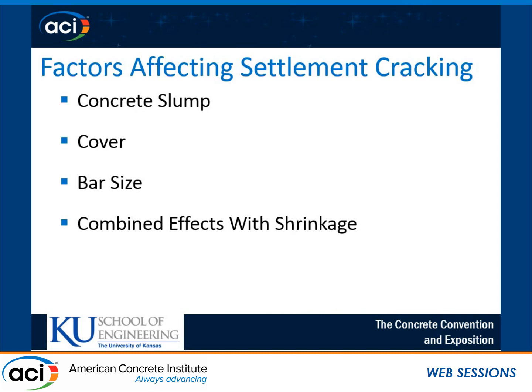So, factors that affect settlement cracking, there's a lot of previous research that has been done in this area showing that increased slump for a given mixture can also increase settlement cracking. On the design side of things, we can help mitigate settlement cracking by increasing concrete cover and decreasing bar size. And you have detrimental effects, potentially vice versa. So bigger bars, that's a bigger surface area for that concrete to flow over, and less cover makes it more likely that that concrete's going to crack. And finally, on the research side of things, we're tying settlement cracking in with shrinkage of concrete. And spoiler alert, the main point of this presentation is to show that many of the crack reduction technologies that are available to help reduce shrinkage also reduce settlement cracking.